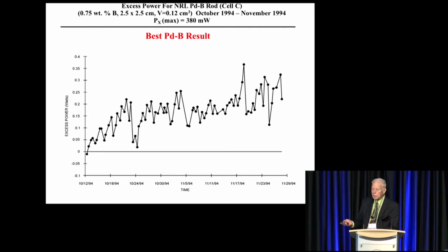And this did prolong the program, the fact that we had this good result with palladium-boron, because one of the major goals of the Navy program was to make our own material. We knew the key in this field is the material problem. And so we wanted to control over the material and make our own material, and we finally succeeded with palladium-boron. We made our own material, and we were getting excess heat practically every experiment.